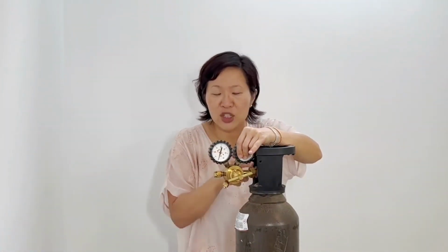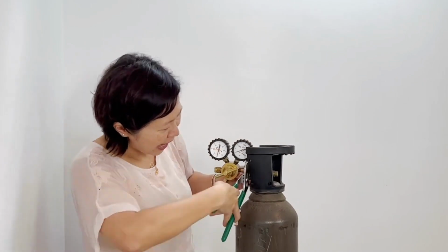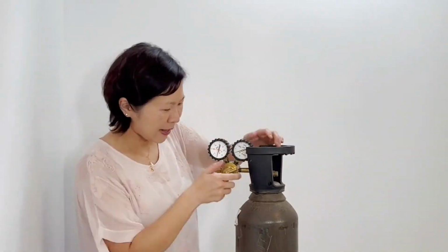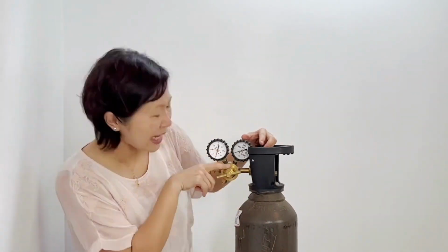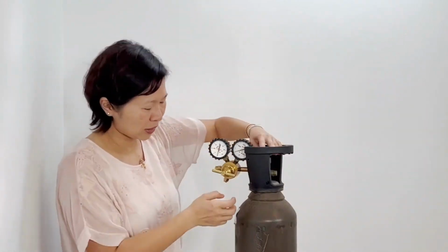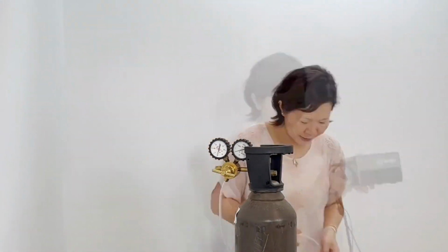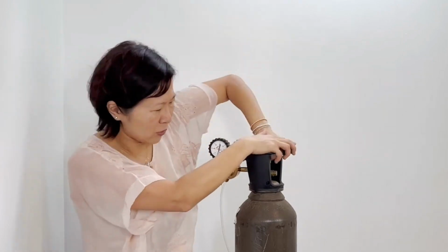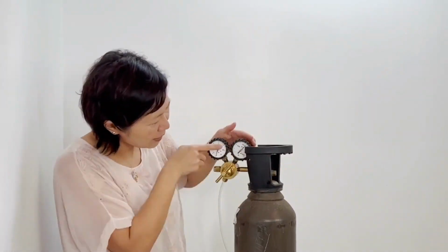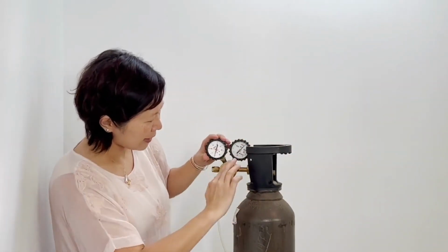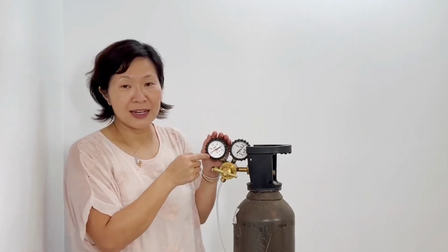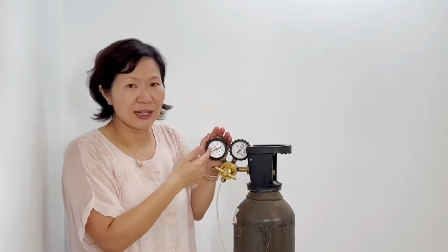So I stand corrected that there is a noticeable difference between the use of argon gas and not when welding fine gauges. I found that argon gas will allow you to achieve a stronger weld at the same power setting. However, that doesn't mean that you cannot achieve strong and secure welds without the use of argon gas. It just means you have to turn it slightly higher power.